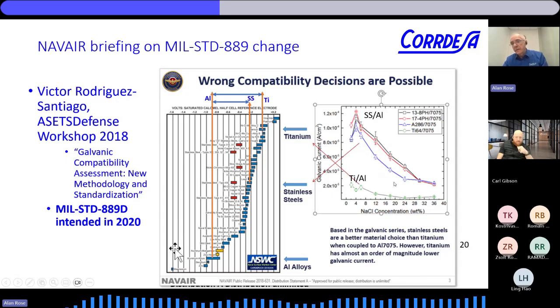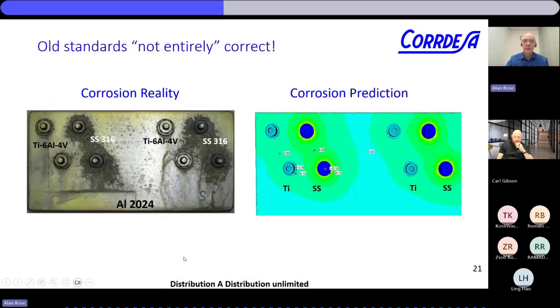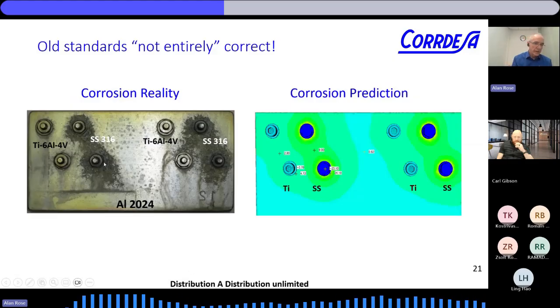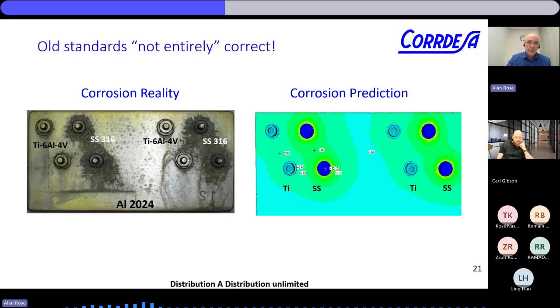But if you look over to the right, if you actually make these couples and you measure the current between them, which is proportional to the corrosion rate, you find that for stainless steel and aluminum couples, the galvanic current is much, much higher. So you can't really have a standard that's driving you in this wrong direction. That was the impetus behind it all. And this is what they were seeing in reality. You get a test coupon or you look at a real system. We have titanium fasteners here on an aluminum plate, and we have stainless steel fasteners, and the corrosion of the aluminum plate is actually accelerated by the presence of the stainless steel.